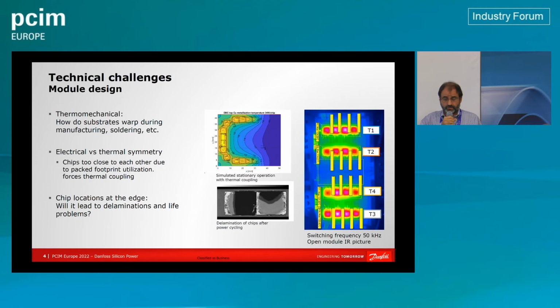Then the other thing is also the thermal coupling during the actual operation. And so here we also see some example of chips which are placed almost on the sides of that module. And of course, what that brings is that the temperature fields are extremely high towards the edges. And if you don't control that, then you have things that can lead to delamination, especially for chips that are close to the edges. Here, what we see on the right-hand side, on the other hand, is some open module pictures with infrared cameras trying to show the good thermal balancing of the chips in actual operation. So this is what you try to strive to.